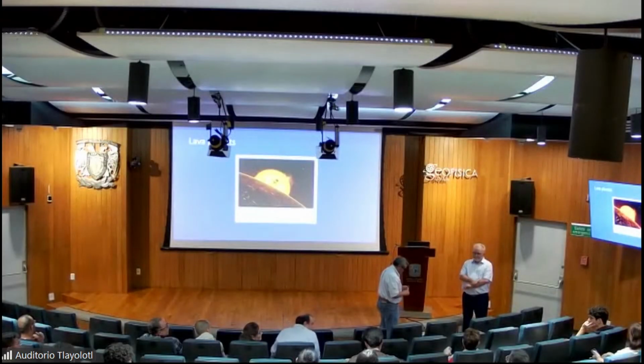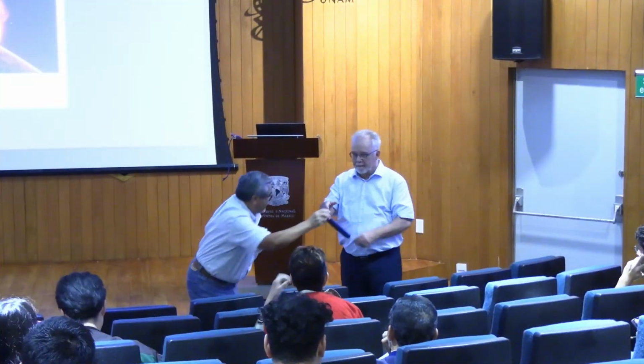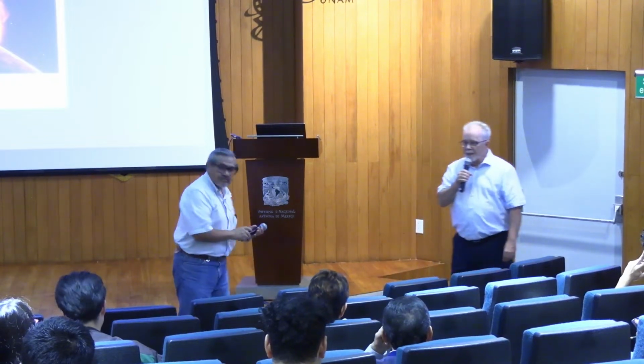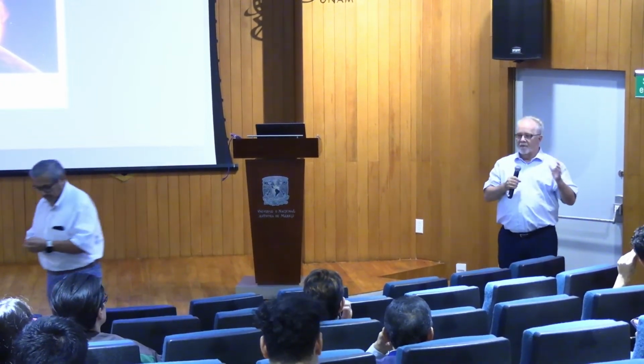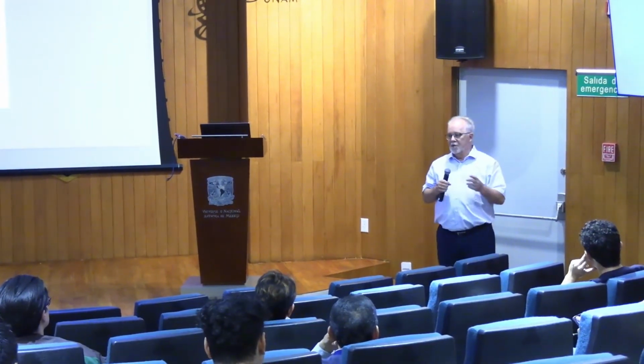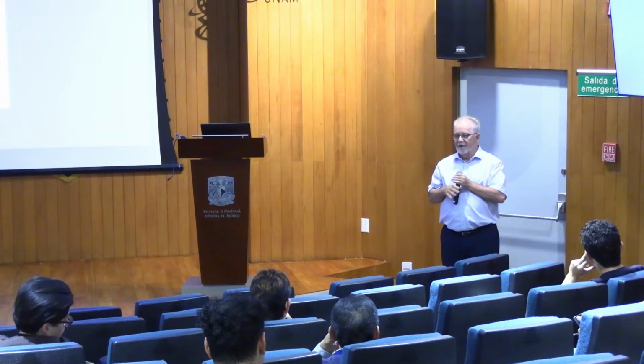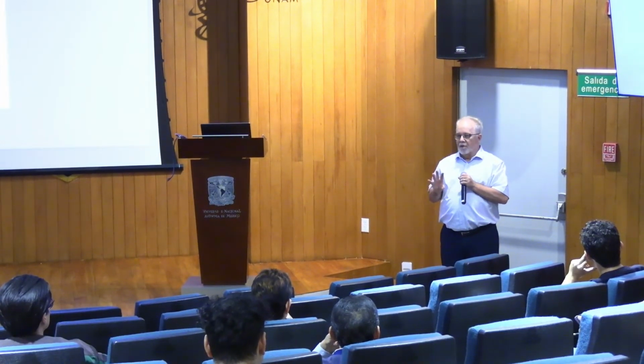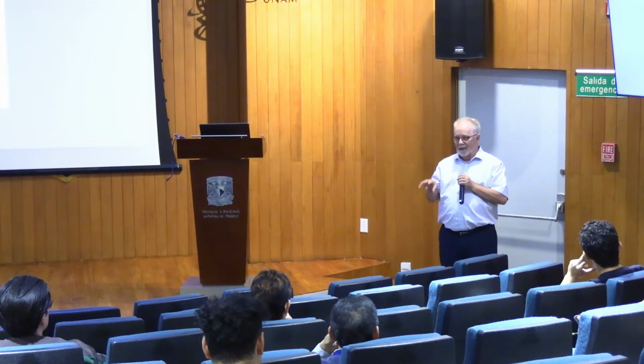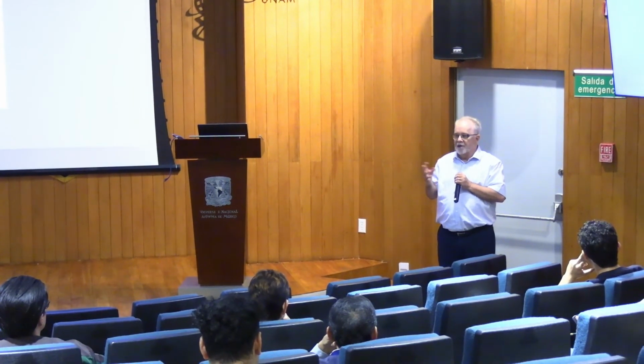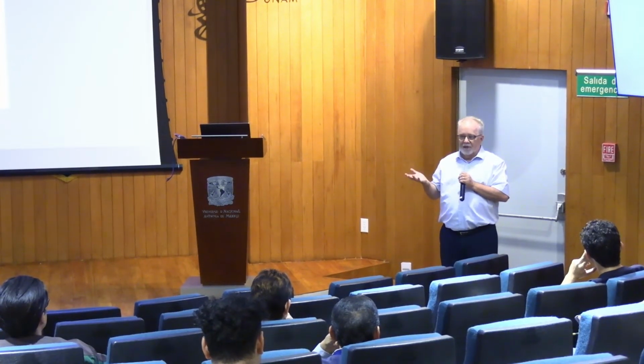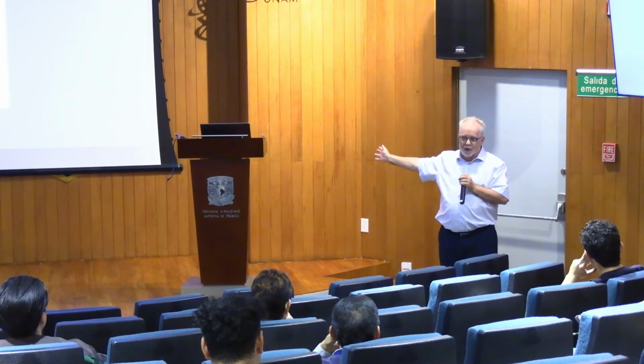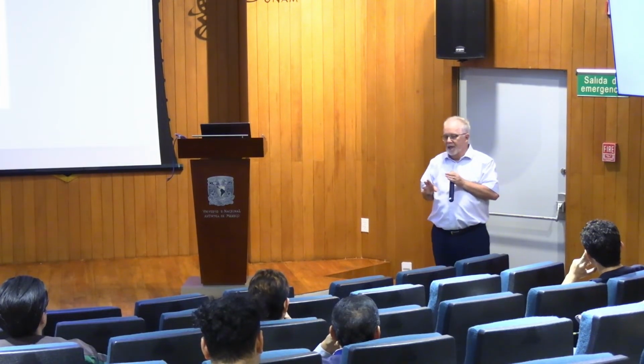If you used an andesitic glass that has higher iron, how do you think the results would shift? Pascal Richet once said to me, I'll never work on iron-bearing glasses. That wasn't very helpful. But his reason was that he had this terrible experience of iron oxide crystallization because he was always doing viscosity measurements in the metastable state well below the liquidus. He was always in danger of incipient crystallization. And he said, whenever we do these andesite measurements, they just go sideways, and we know we're losing it to microcrystallization. So the general case would be that it's strongly dependent on the iron content, the same as in rhyolites.